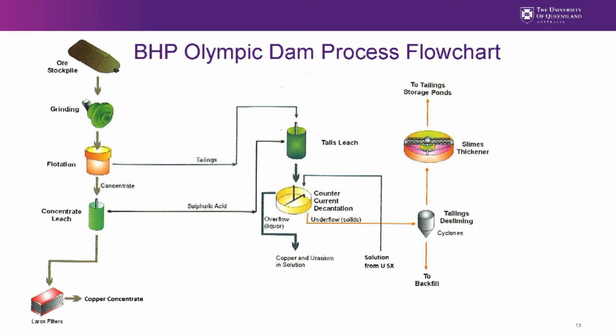Copper is eventually recovered after electrorefining, and the gold and silver are recovered from the slimes during copper electrorefining. The tails from the flotation process are further processed through a tails leach process. The concentrate leach and the tails leach are integrated with the solutions going around, and it's a sulfuric acid solution, which is produced at the smelter.